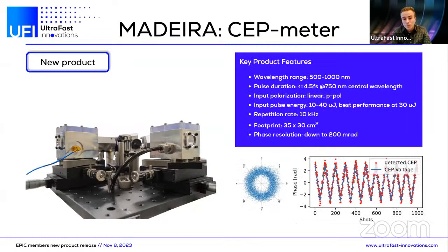And our product is especially designed to fit titanium sapphire based laser systems, which usually operate in a wavelength range from 500 to 1000 nanometers. And this is where our device works best. Our device offers a long-term stability, which is very important because it can measure the carrier envelope phase of each single laser pulse over a very extended period of time of several hours or up to several days. And here you see an exemplary data set. So each small blue dot here corresponds to a single laser shot.